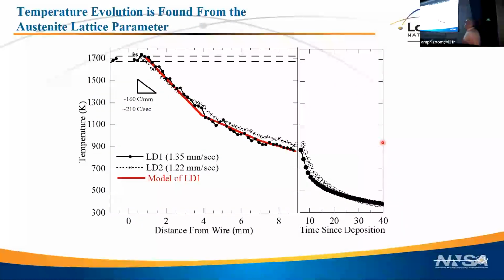So here's the temperature as a function of time. And again, now we have infinite, because we've set up a quasi-steady state, we have essentially infinite time resolution. So here's the material right at the melt pool. So when we do see solid here, it's again right in the melting temperature range of steel. It cools now because we continue putting heat in it. When we did the point deposition, it was just a quick drop of material and then it cooled very quickly. Here we keep dumping in heat because we're depositing along this line. So that slows the process down.